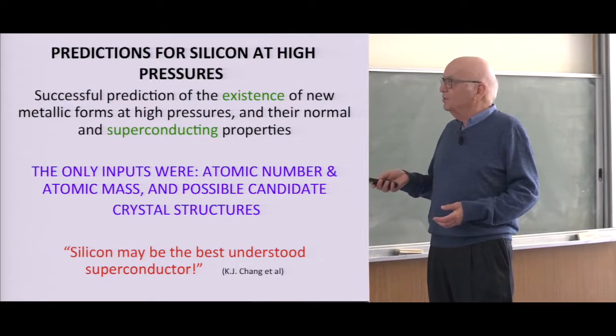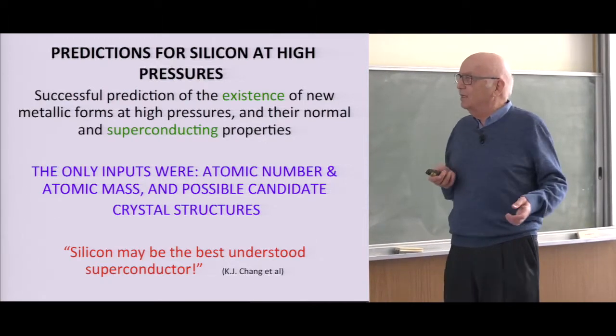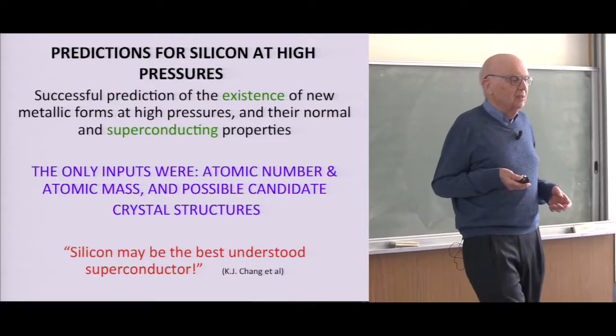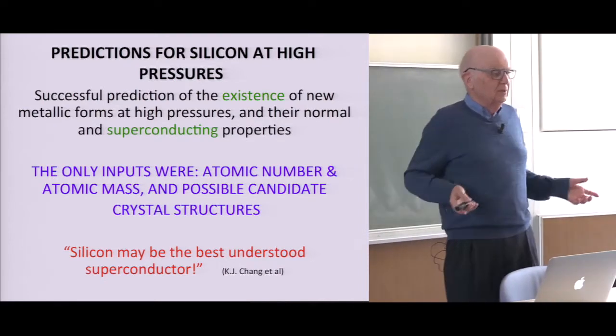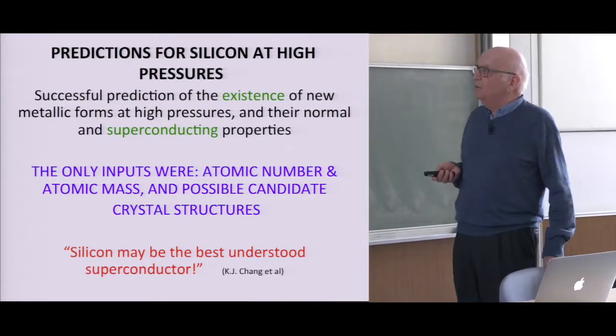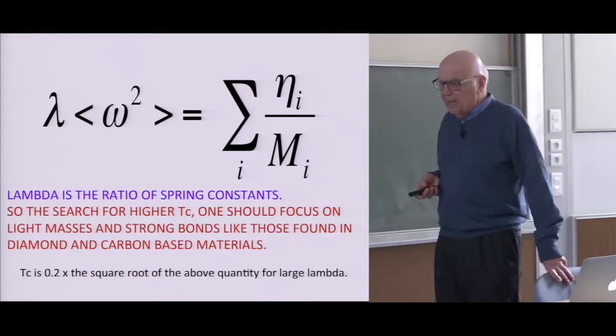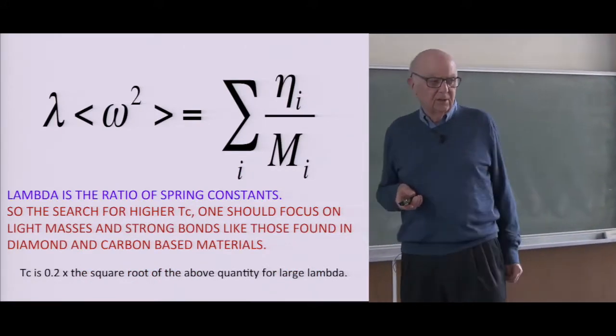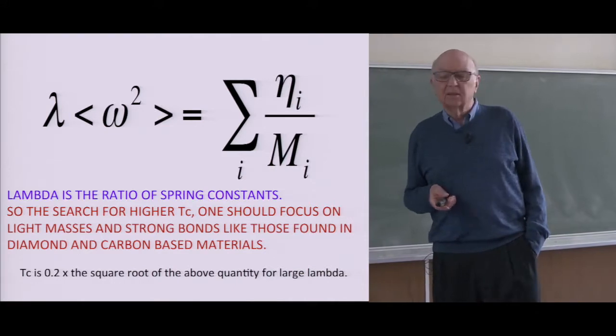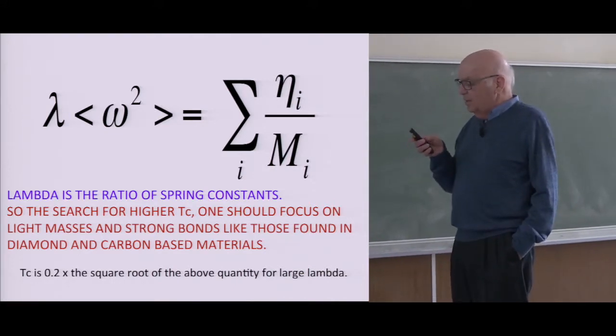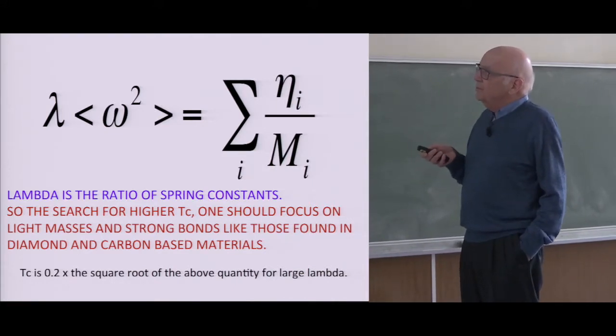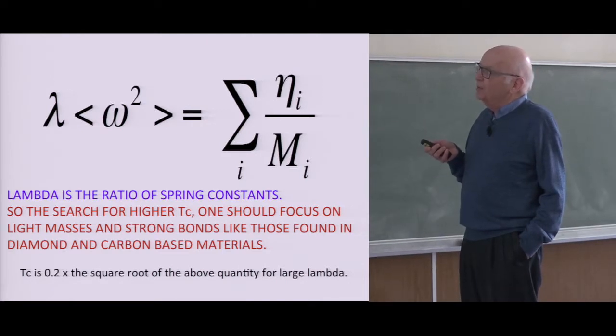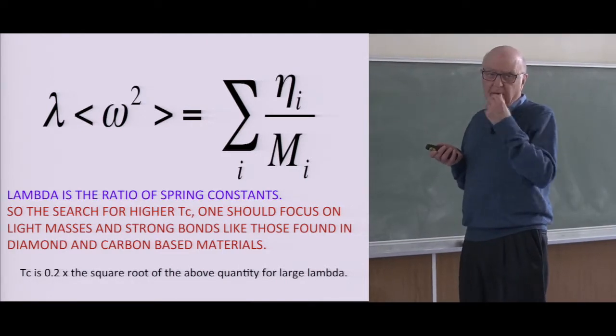And my former student had made the statement that perhaps silicon is the best understood superconductor, because you could start from first principles. So the question is, if you start from first principles, how high can you get in transition temperatures, and what's the best system? Well, this is an interesting formula. This is the hero of superconductivity for electron-phonon interactions.